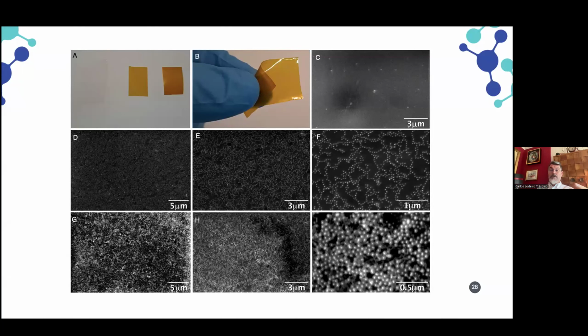Then you can use this polymer as a starting material to create every material you like, with this polymeric film having the property of being antibacterial. Panel C is showing you that the polymer is porous, and this porosity allows the release of the silver ions from inside to outside. It could be used, for example, for microbiology applications in a hospital.